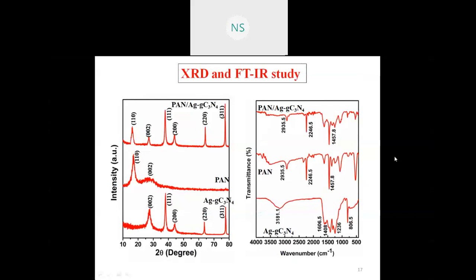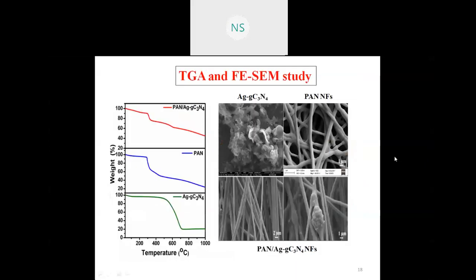In the FTIR study, all the functional groups are present, those appearing from polyacrylonitrile and those from the Ag-g-C3N4. All these peaks are there. There is also a far IR range, which is not shown here, but mainly we have shown the presence of polyacrylonitrile functional groups, which shows the presence or formation of that nanofiber. Next.